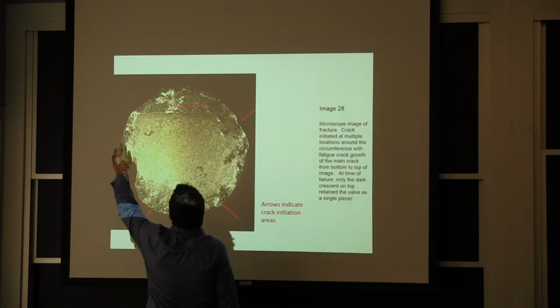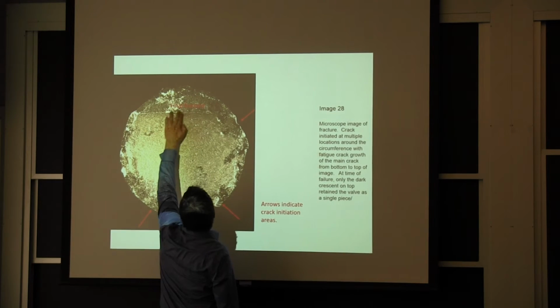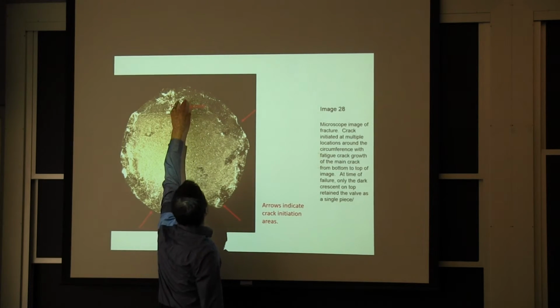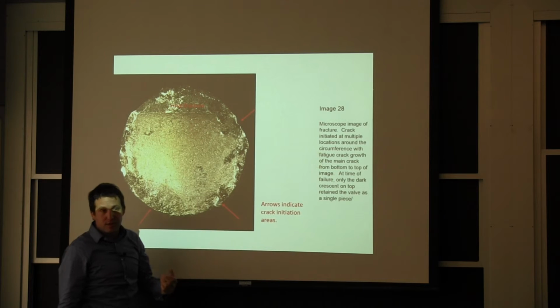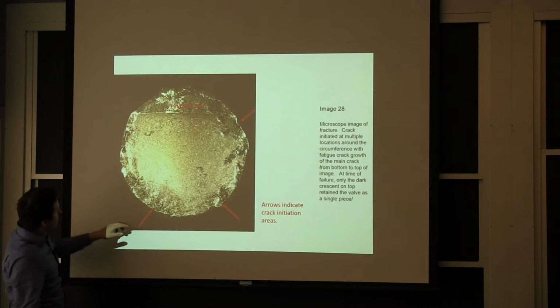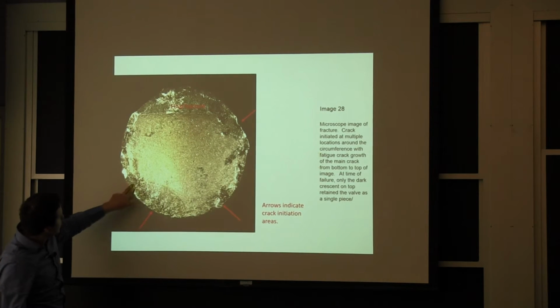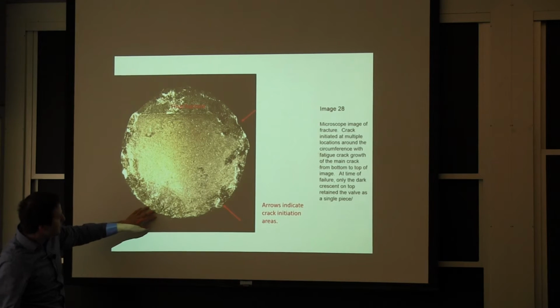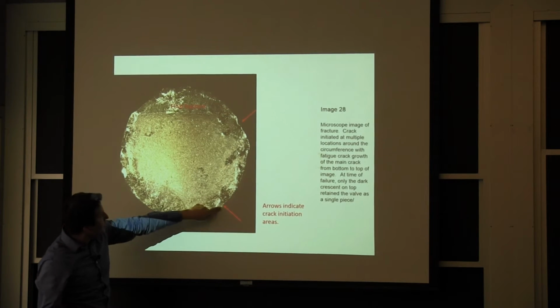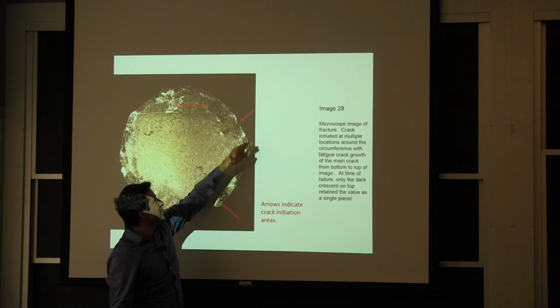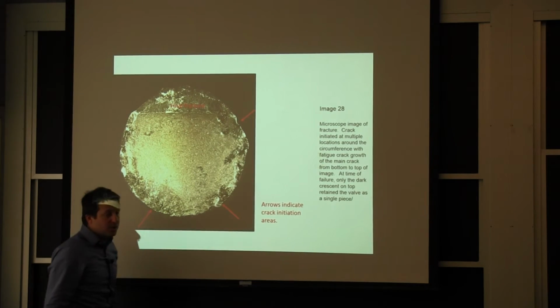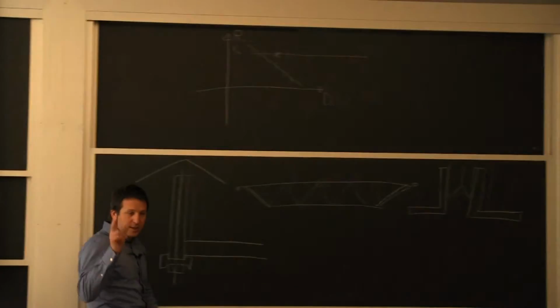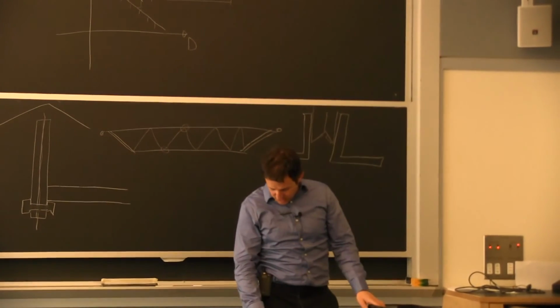So final fracture, there's this line here. This is when you reach the fracture toughness. There was only so much material left, very little, okay? And looking on the other side, I have this beach mark here. So this is one area where the crack started. I have another beach mark here. Oh, it started here too. And then this is harder to see from here, but I kind of knew there was an initiation site there too. Another situation with 3 initiation sites.